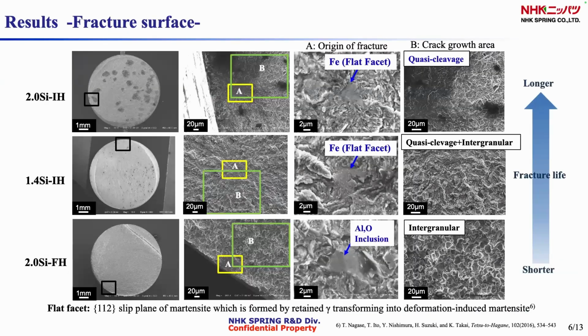These are the fracture surfaces of these specimens. It was found that the origin of fracture for IH tempered steel was inclusion or flat facet. In previous research on martensitic bearing steels, the flat facet is said to be the {112} or {110} plane of martensite, which is formed by hydrogen-induced deformation of martensite. I will explain the flat facet in detail in the discussion part.